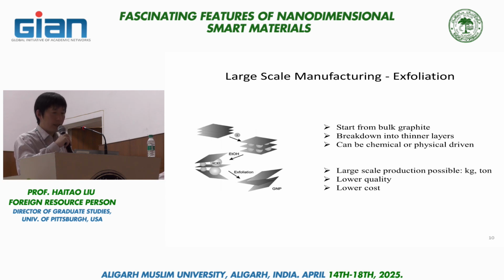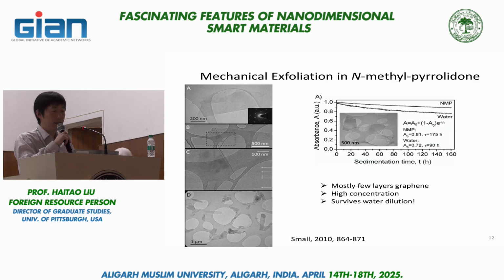So let me give you an example. This is a process developed by a group in Northern Ireland, I think, the Coleman group. They reported a variety of this mechanical exfoliation process. In some cases, you use a solvent that is friendly to the 2D material. In this case, it's graphite exfoliation, and they use the solvent called NMP. Okay. And this solvent has a surface tension similar to that of graphite and graphene, and that makes the solvent-solute interaction particularly amenable to stabilizing graphene flakes in the solvent.